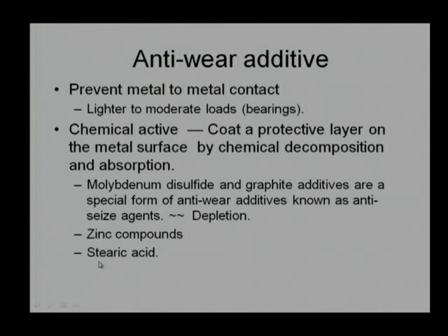We have already discussed stearic acid, which is a boundary additive, a polar lubricant additive. It has a polar head to get attached to the surface, and in the way we mentioned about the dispersion, they have almost a similar kind of physical form. Zinc compounds, ZDDP, is one of the common additives used as an anti-wear additive. Even molybdenum disulfide and graphite can work as anti-wear additives, because they reduce interface shear strength, they reduce the friction. So, they can be put in the category of anti-wear additives.